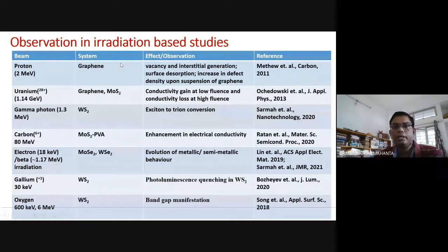Now, observations in irradiation based studies by others and ours, starting from proton beam to uranium, gamma photon, carbon beam, electron, beta, gallium and oxygen. You could see a lot of changes, a lot of interesting properties. For example, in one case, vacancies and interstitial generation, then surface desorption in case of graphene, then conductivity gain at low fluence in case of graphene and MoS2, then exciton to trion conversion, which was very interesting. In fact, referees were very much appreciating this particular work because of exciton to trion conversion.